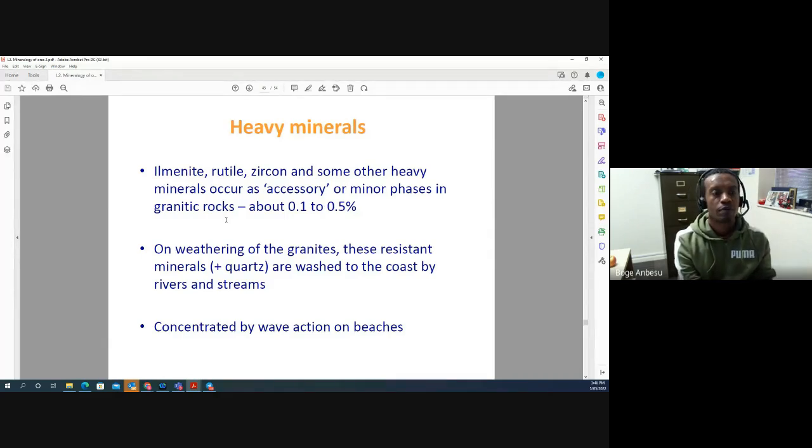Once you have the excess silica removed, now you have, say, ilmenite, zircon, and rutile. We know ilmenite is magnetic, and we know rutile, for example, conducts electricity, or is electrostatically conductive, and zircon is not magnetic and is not conductive.